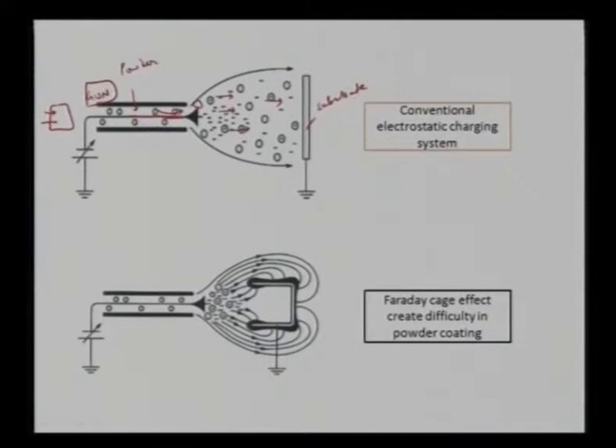So that is the overall philosophy: we apply a blower, it carries away the powder particles, and then it encounters an electrode which is centrally located in the gun. That makes the powder particles get charged, and the flow of air blown from the other end carries the charged powder particles away, and once they strike the substrate, they can transfer the charge back to the substrate.